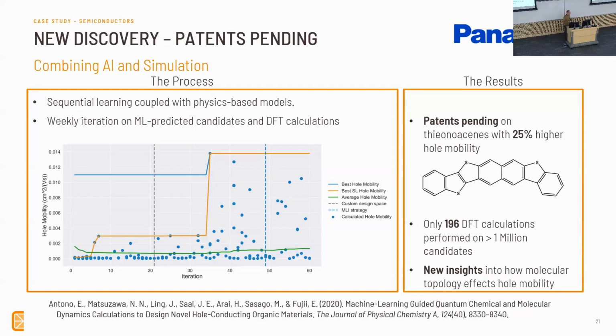Because the machine learning model is somewhat cheap to run, we could run it on an order of magnitude more molecules without much effort. Once we did that, after about 10 iterations or so, we were able to find something significantly better than anything they had seen before. And in fact, it was pretty interesting. If you look on the right, we found this particular class of molecules called thienoacenes. I can't pronounce that, but it has about 25% higher hole mobility than anything we had found before.